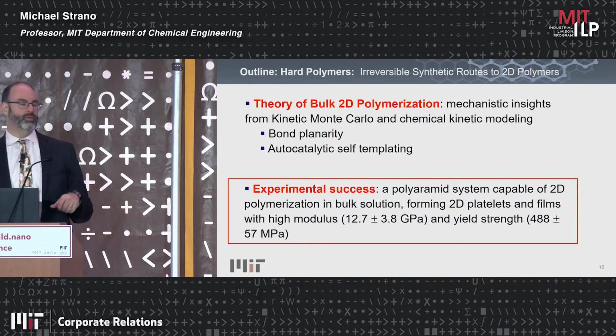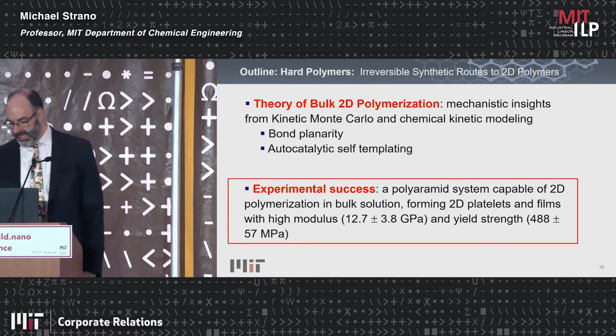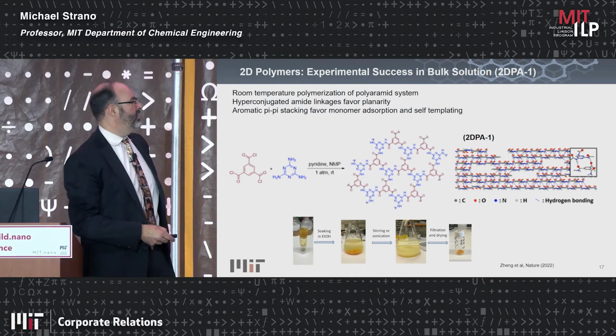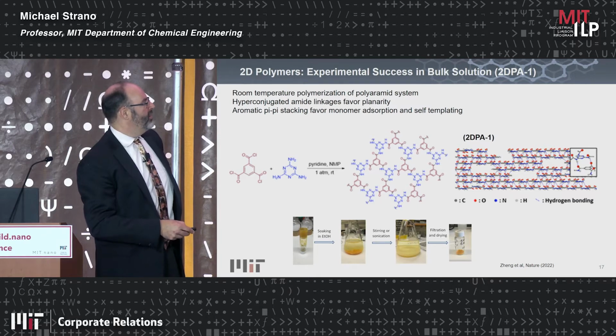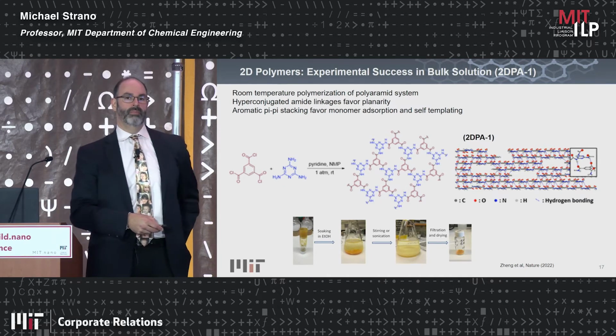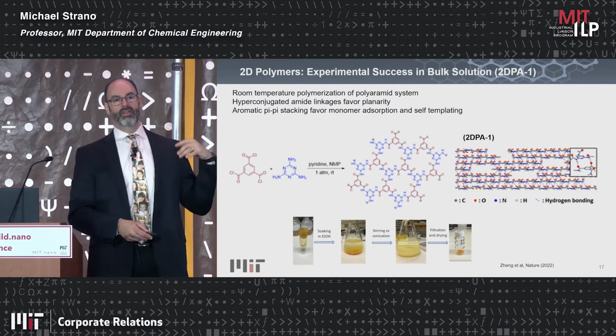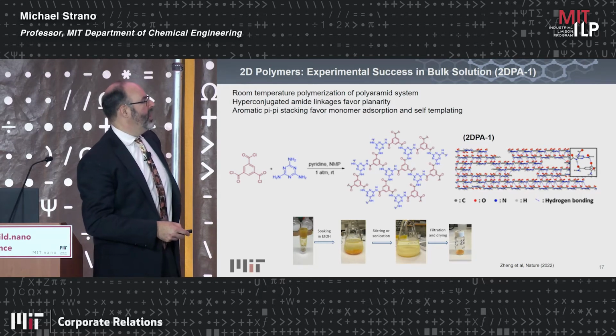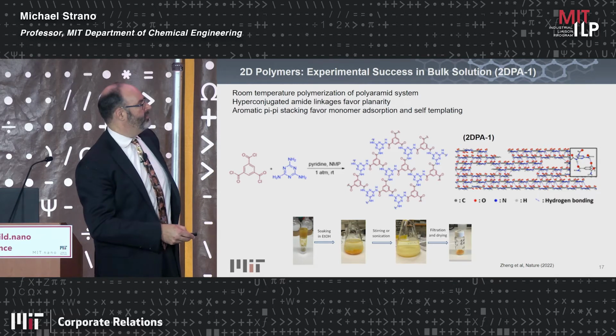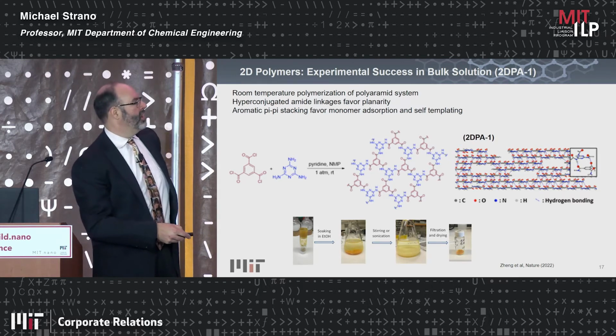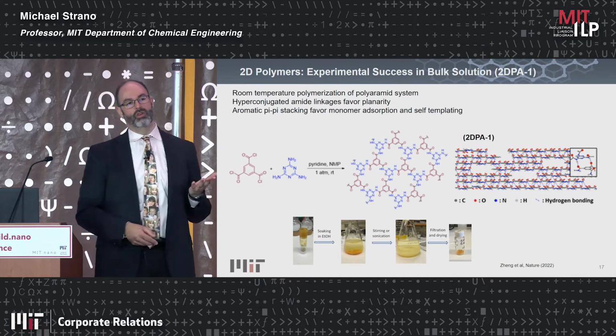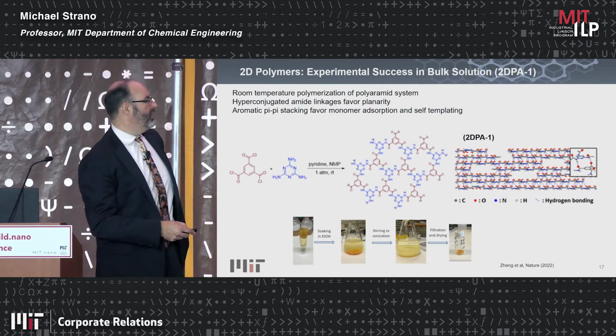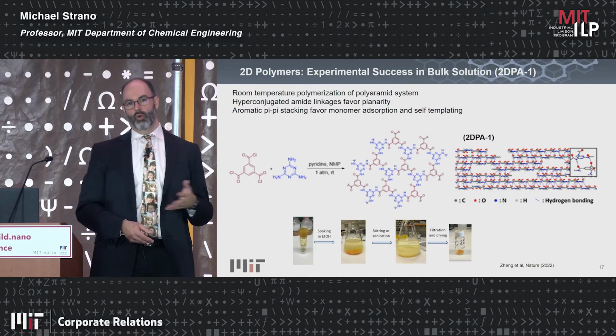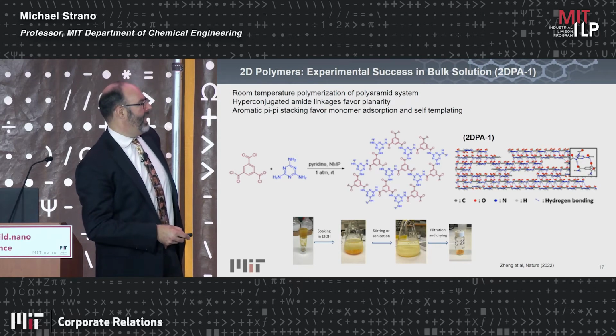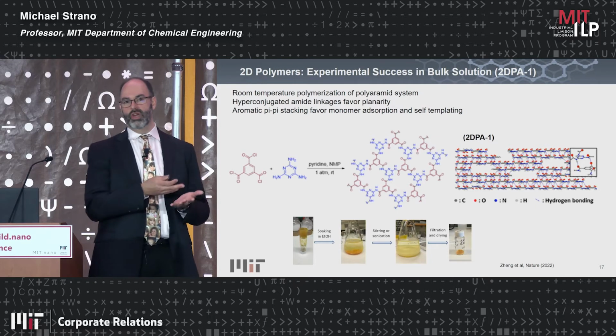Okay, so let's talk about our first experimental success with this. Is this cousin of 2D Kevlar? It's a fascinating material. It's amazing. These monomers, this is an acid chloride. This is a molecule called melamine. These are exceptionally cheap. We do not have to synthesize them. You can buy them in bulk quantities. If you polymerize this, you get this polymer. It forms these platelet-like stacks. And this is my colleague in chemical engineering, Heather Kulik, helped us to elucidate the structure. You get these, just like Kevlar, the material likes to hydrogen bond to itself. And so one of the first things we realize is that the material forms exceptionally strong, self-organized films. And the reason why it does that is because it has these chemical groups that like to hydrogen bond. They like to stick to each other like Velcro.